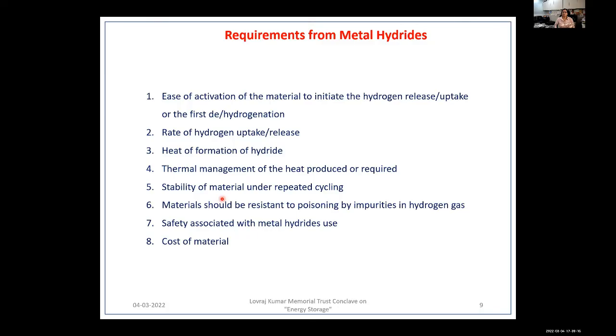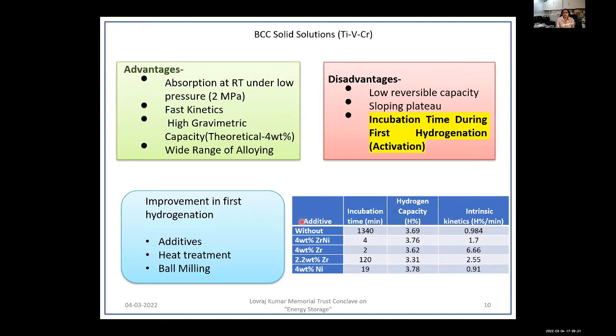These materials should be stable under repeated cycling, so cyclability is important. They should not get poisoned by impurities, and the safety associated with using metal hydrides in such tanks is also important. At the same time, cost. To give you an example of a BCC alloy, like the titanium, vanadium, chromium alloy, it has the advantage that absorption takes place at a lower pressure, 20 bar, and at room temperature. It has faster kinetics, and the theoretical capacity is 4 weight percent. You can have a wide range of alloys by changing the composition. The problem that remains is the sloping plateau and an incubation period.